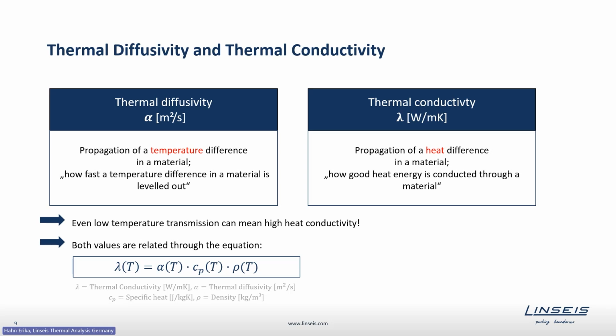The thermal conductivity describes the propagation of a heat difference in a material, so how good heat energy is conducted through a material. As mentioned, both properties are related to each other. This you can see here on the bottom of the slide, where the thermal conductivity is just a product of thermal diffusivity, specific heat capacity, and density. All of these properties are temperature dependent, so it is very important to test all of these properties in dependence on temperature.